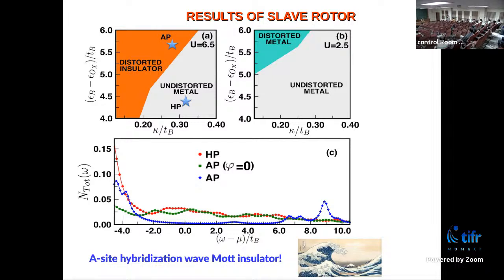No, these are not like that. First of all, I did not follow your question correctly, and I don't know whether I'm giving you the right answer because I didn't quite get your question. So all the anisotropy is because if you look at this cuprate superconductor crystal structure, even structure-wise, they are highly anisotropic. If you measure their resistivity in plane and out of plane, they are very different. So they are very anisotropic to start with.